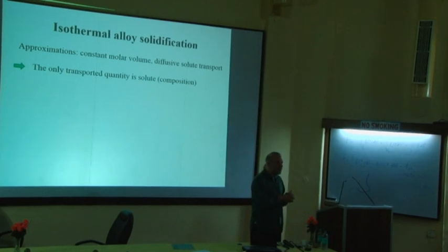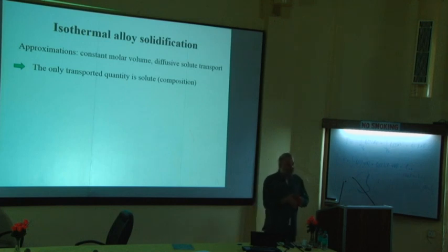What is the motivation for that? It is that we have seen at the very end, if I do the bottom-up approach, that is, if I write a model that corresponds to some microscopic reality, it will be completely useless for practical simulations because I will be stuck with interface thicknesses that are of the order of 1 nanometer. And in order to be able to properly work with interfaces that are much larger, the tool to use is this matched asymptotic expansion technique, which is kind of complicated. If I want to do the calculation that gives you the magic formula, it takes about 15 pages.